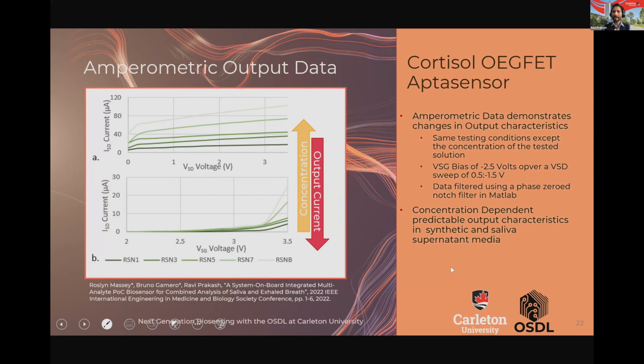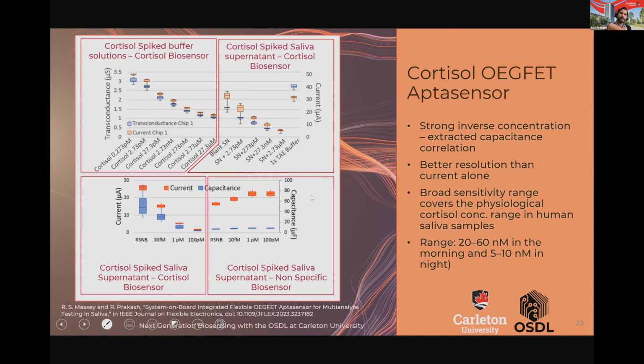So I mentioned these are transistors, which essentially means that we will be generating amperometric output. So the current response from the device has a correlation to the concentration of a target analyte. In this case, in this plot, it's cortisol, varying levels of cortisol in saliva supernatant collected by a student in the lab. You can see that there is a correlation. It's an inverse correlation, which is nice. So essentially, with lower concentration, our device is sensitive. We also have a nice log linear range for this sensitivity. It's a broad range sensitivity, which is great for a non-invasive point of care technology.